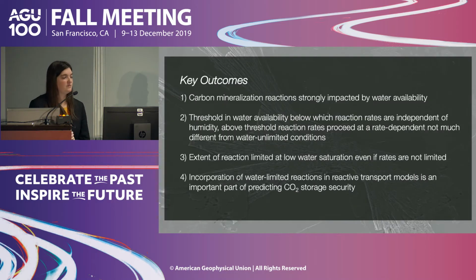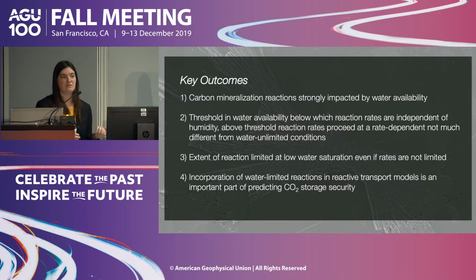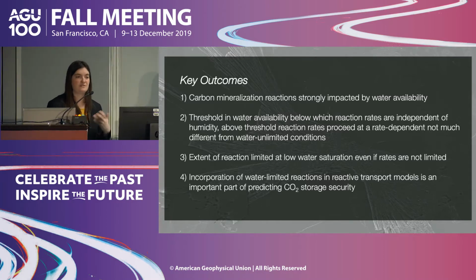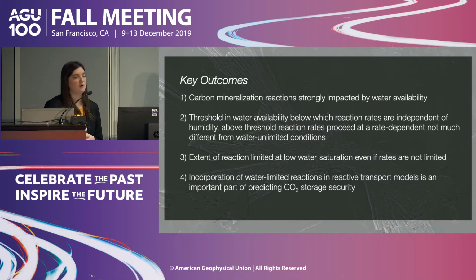And so in summary then, what we've observed is that carbon mineralization reactions are strongly impacted by water availability, but it's more an impact on the amount of reaction that can occur versus the rate of reaction. And this is an important distinction for how we can choose to model these systems. But ultimately, we're still missing a bit of a mechanistic approach here, and that's what we'd like to move towards to better incorporate water limitations in our reactive transport models, both for modeling CO2 storage security, but for modeling in general in these water unsaturated systems. Thank you.